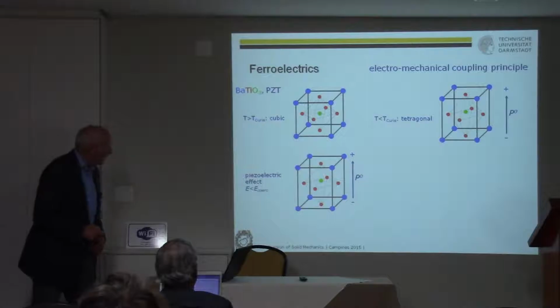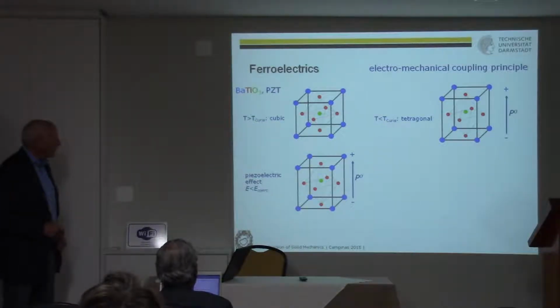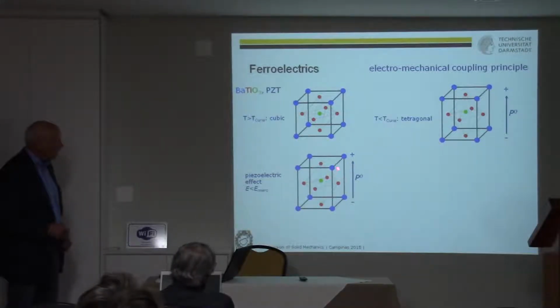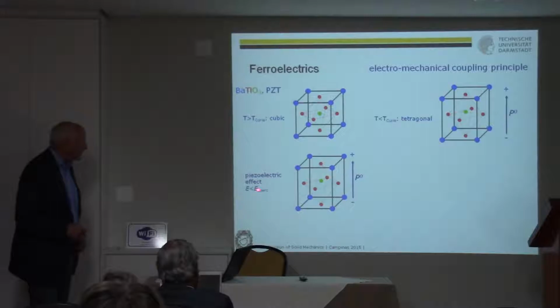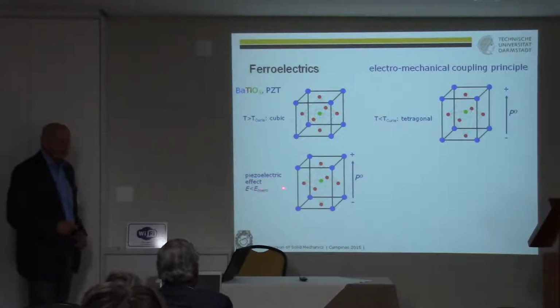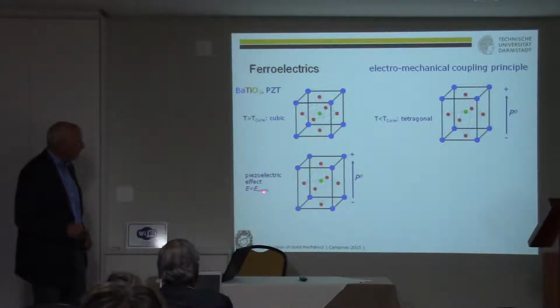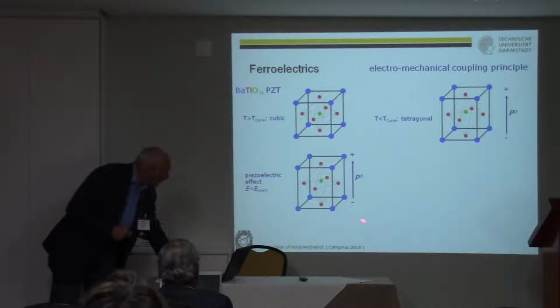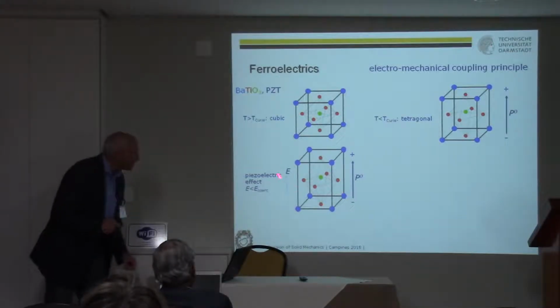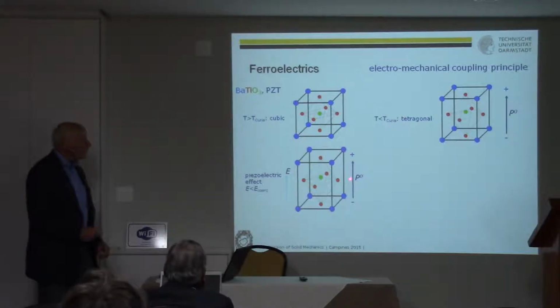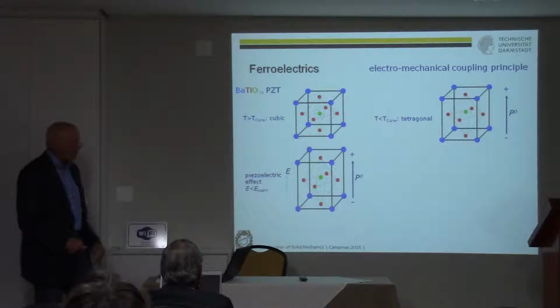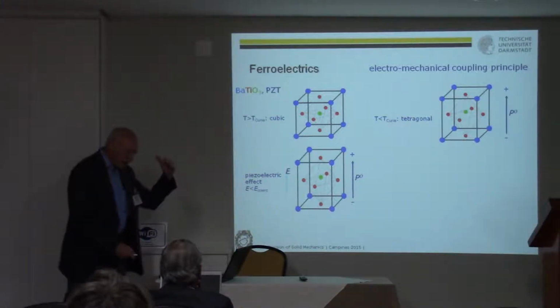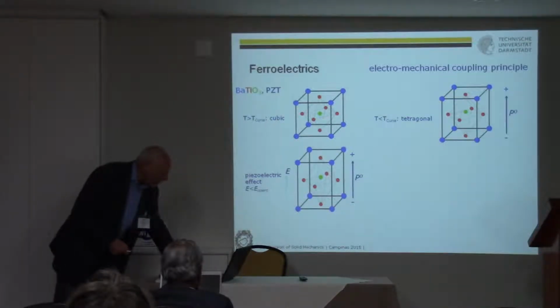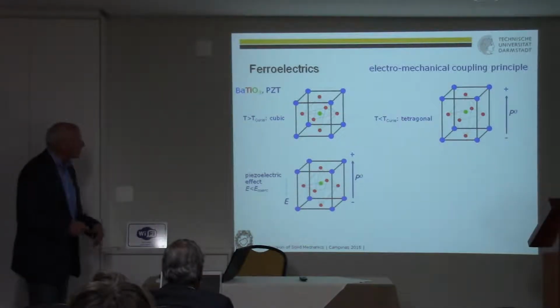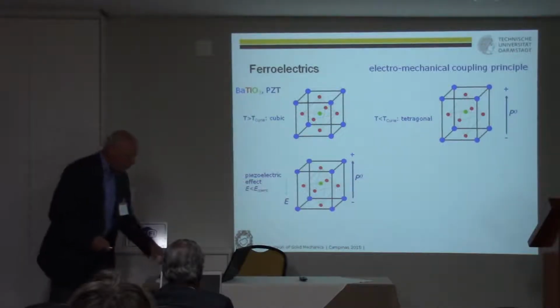Now let's see. When we apply an electric field to such a structure, what happens? If the electric field is relatively low, below the coercive electric field, nothing special is happening. Let's see what happens if we apply the field in the direction of polarization. This leads to an elongation of the tetragonal structure. You have a displacement or a strain of this structure. If you apply it in the opposite direction to the polarization, it will be compressed.